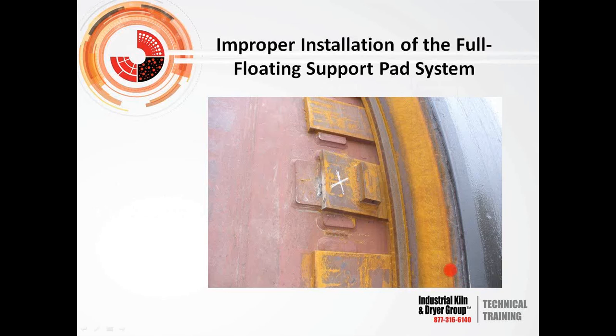You want to explain this, John, as far as what not to do? Yeah, this comes back to what happens when you go with these really narrow support pads on units. There's not enough cross-sectional area, and if you don't get everything snugged down tight when you're installing them, what can happen, like in this case, is that this tire passed through the rollers, and when it hit the rollers, it bent the bar, bent the pad. So now the pad is bent and not doing an effective job, and it'll jump over these end blocks, and it causes a lot of issues mechanically.